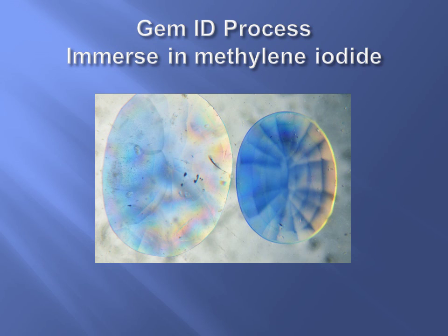You can see by this picture that the color is concentrating at the facet edges. That would be an indication that this stone has been diffusion treated, which is a surface treatment that can be polished off. In this illustration, this is a natural stone where you can actually see straight through it, so we know it hasn't been diffusion treated. There is a new treatment around now called beryllium diffusion treatment, which is a little more difficult to identify because we need to study the inclusions to see indications inside the stone of any change that has taken place during the process.